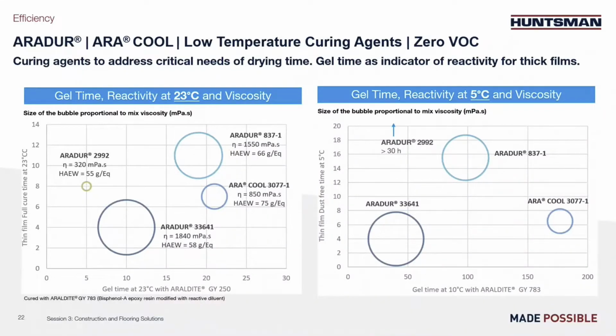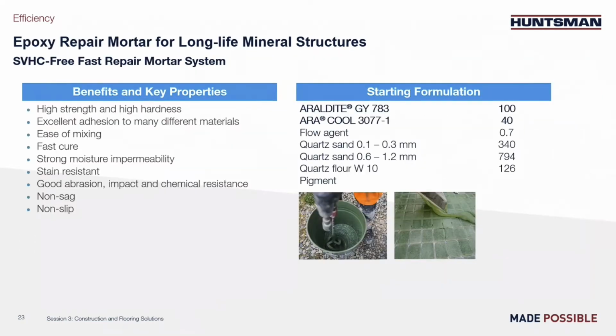It is low in viscosity, it has relatively long pot life and dries pretty well at 5 and 23 degrees. It is a very good choice, for instance, for a zero VOC repair mortar system, as I present on this slide. So here we focus on mortar. Generally, the hardener needs to be low viscosity, enabling a very high filler loading, about 90%. Having this loading allows high strength and high hardness, as well as good chemical resistance because of the organic part. For fast repair, a fast cure hardener is generally preferred. And here the Aracool 3077-1 in combination with standard low viscosity Araldite GY783.